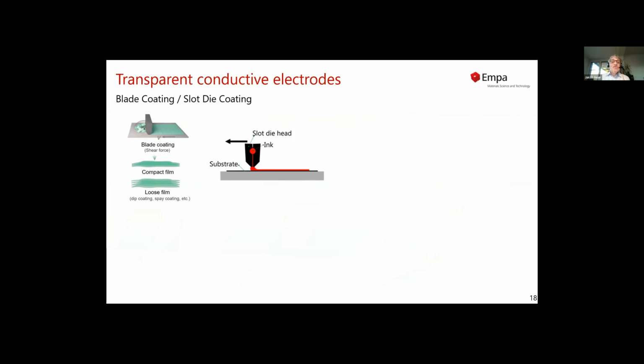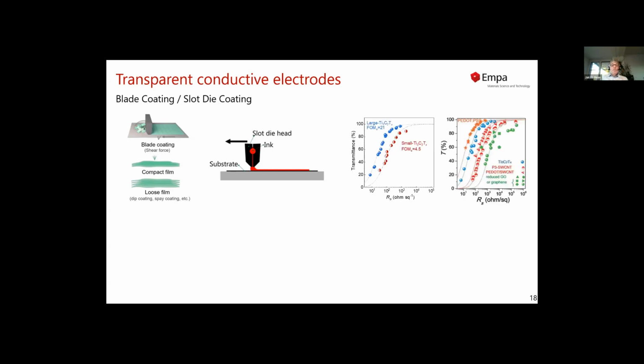MXenes stick out for very high, almost metallic conductivity. So what we were looking at is whether, via a slot die coating process, we can replace transparent conductive electrodes, like for example ITO, which is needed for solar cell applications. It's also needed for displays, and it's used in any smartphone, any type of display. For that you need high conductivity and you need transmittance. And if you dive deep into the physics of electro-optics, you will see that conductivity and transparency are correlated to each other.